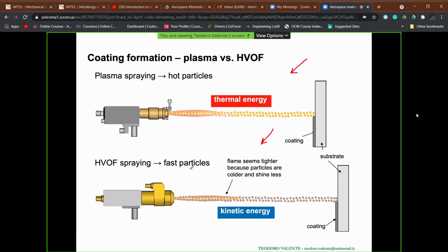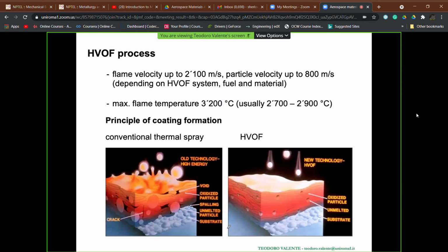Instead, if we are talking about HVOF, they are processes which are controlled by kinetic energy, due to the very high particle velocity and thus gas velocity values that we can experience. We set this number in terms of particle velocities. Maximum values can reach around 800 meters per second. For the flame velocity, we can experience values, corresponding obviously to the maximum particle velocity, which are higher than 2000 meters per second.